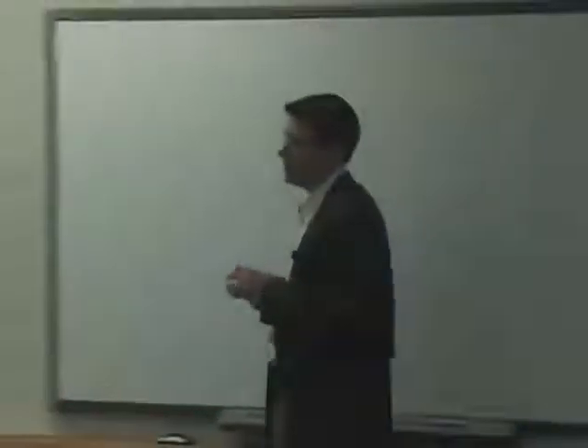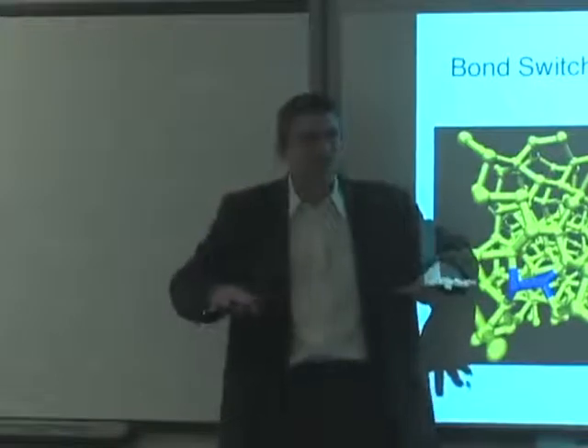Okay? And I won't go into the details, but what we found is that it has to do with basically the delocalization of the strain. You see, if you concentrate strain really tightly, then the hole has to be concentrated, and that makes its kinetic energy high, and it doesn't like that, right? So what the hole really likes is to be spread over about two or three bonds, right? And so there are just the right kinds of strain that do that.